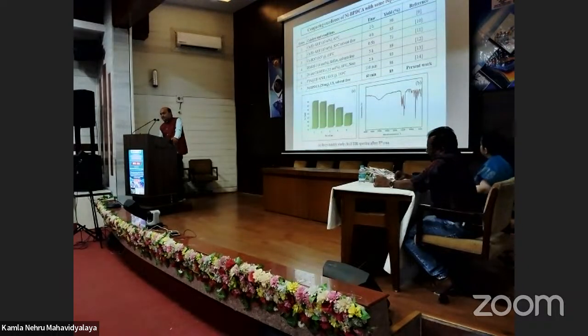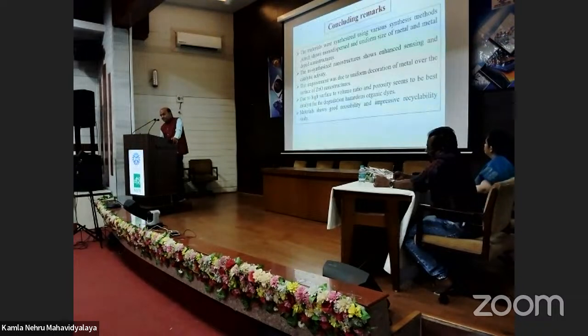So if you look into this, 20 milligram of the catalyst is sufficient. Under solvent-free condition, we get 89% yield as compared to the others. We have more selectivity. We have done the selectivity to the position, that is with the help of the alkyl group. If you look into this, 3,4,5-trimethoxybenzaldehyde shows 97% yield within 30 minutes. This is the comparative study. The catalyst is active up to the 5th cycle.